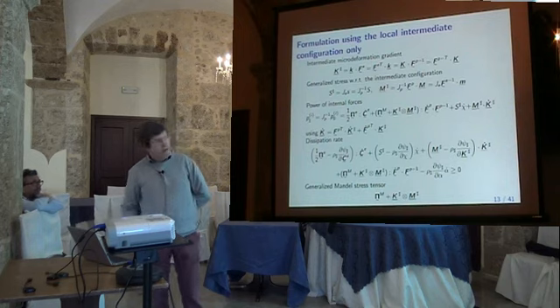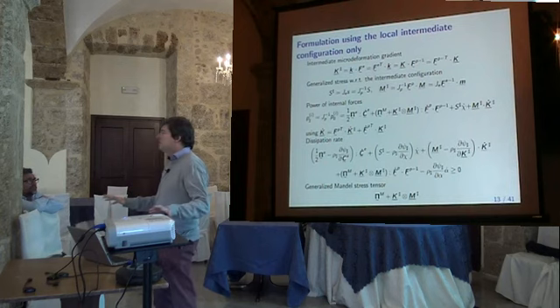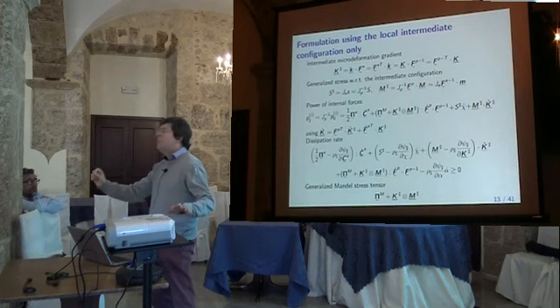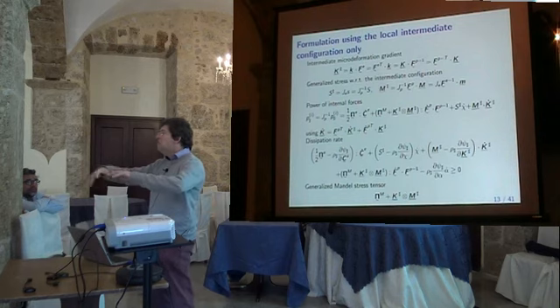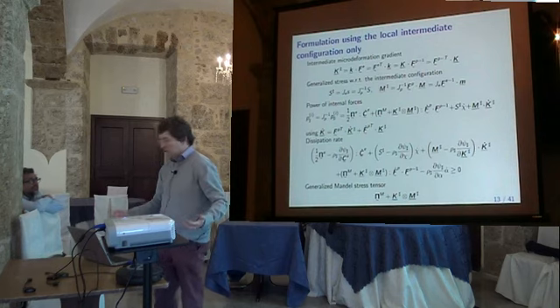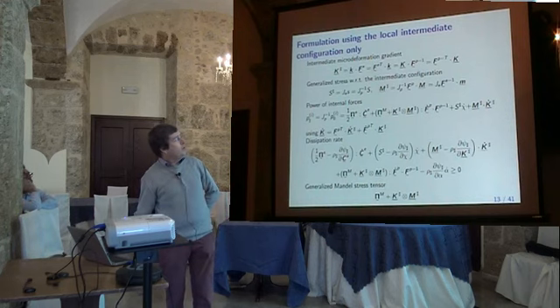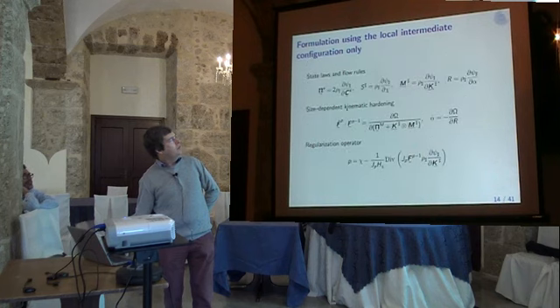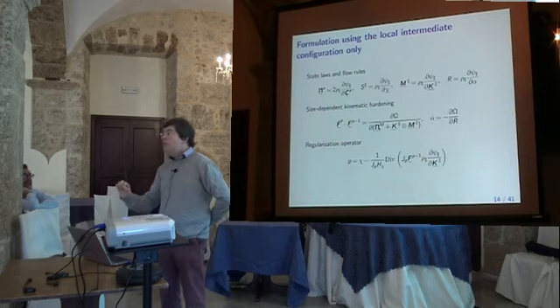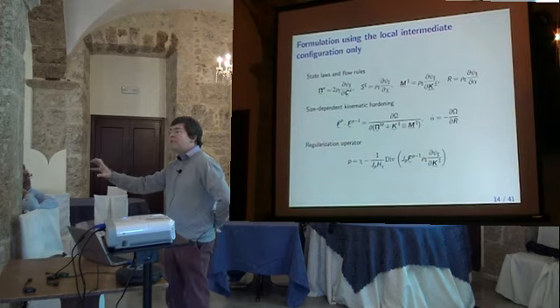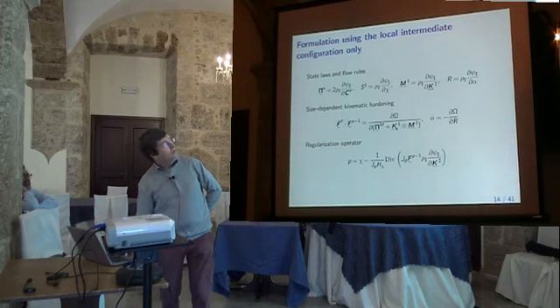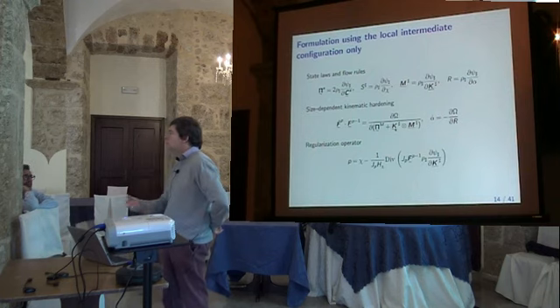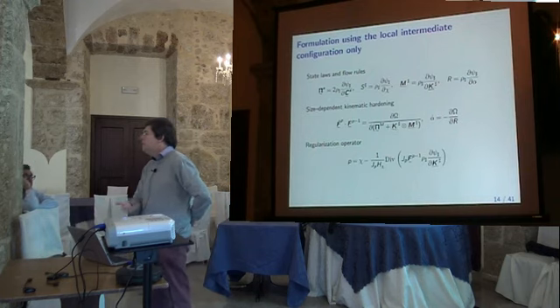And you can do all the work, and there is a difference here. There is no Laplace equation because of the lack of compatibility of the intermediate configuration. You have no explicit equation. You have a complex form of the partial differential equation. And what is also important in this one is that the model is a bit changed. The Mandel stress alone is not anymore the driving force for plastic flow. You have to add something coming from the relaxed gradient of micro deformation. And this is kinematic hardening.